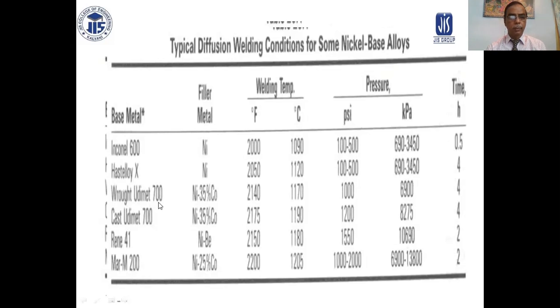Udimet 700, nickel, 35% cobalt, 1170, 1000 psi. This is 4 hours. Cast Udimet 700, nickel, 35% cobalt. This is 1190, 1200 psi pressure. That is 4 hours.